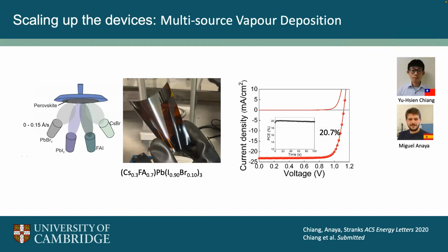I talked about the challenge of scaling up. A lot of these cells that we make are relatively small. They're about 2.5 by 2.5 centimeters, about 1 inch square, so this size in the lab. A big challenge is, of course, to take that to a mini module and then to full module size. Recently, we've been looking at vapor deposition of these samples. So here we're vapor depositing, so we sublime the materials onto the substrate, and you form really uniform films that way, and also you can do that with a very large area.